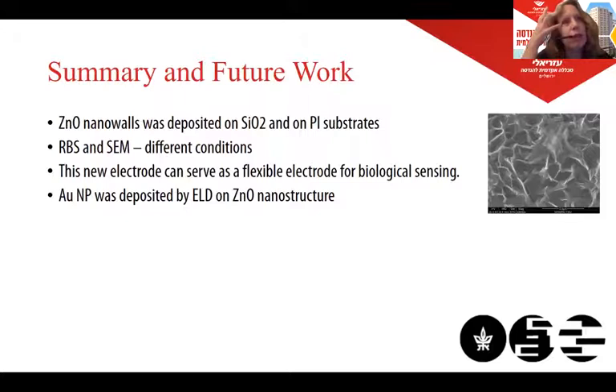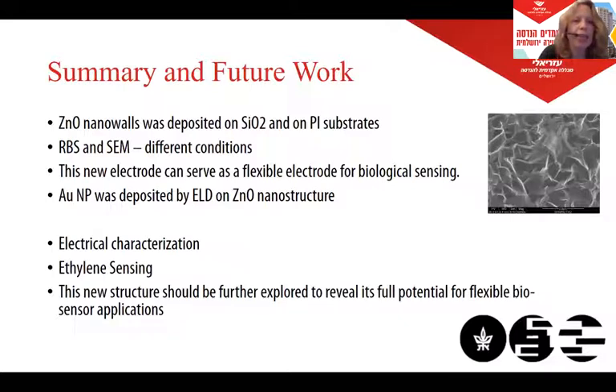So to summarize what we did and what we will do in the future, ZnO nanowalls were deposited on both silicon oxide and polyimide. We did Rutherford scattering and SEM for different conditions, different times, concentration, stirring, without stirring. And we think that the new electrode can serve as a flexible electrode for biological sensing. And we also, in parallel, studied gold nanoparticle deposition, electroless deposition on ZnO nanostructure. Now we want to combine the two things, the electroless deposition of gold on nanowalls, ZnO nanostructure, and we'll do electrical characterization, ethylene sensing, and we believe that this new structure should be further explored to reveal its full potential for a flexible biosensor application.